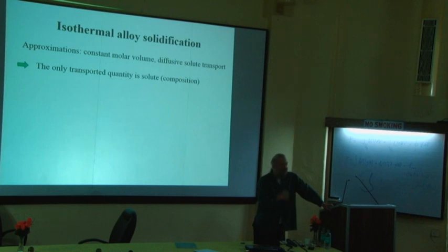If I'm in an alloy, the relevant thermodynamic potential is the grand potential, and the variable that would be equivalent to the temperature is the other intensive variable, that is the chemical potential. So if I write my alloy phase field model in terms of the grand potential and the chemical potential, the equations have exactly the same structure as the one for the thermal model that I have developed here. Okay? So there is not much new in principle. It's just that you have to think through the whole thing again in different terms, but Abik is right, I can do that tomorrow. Okay?